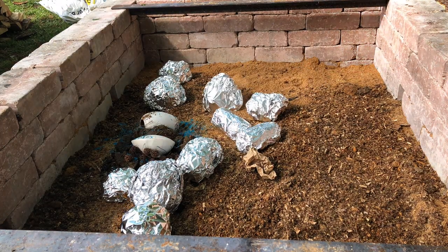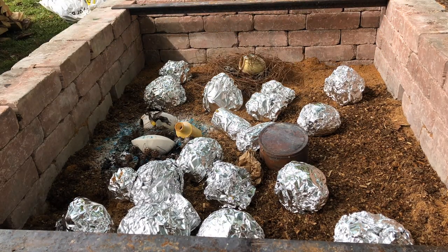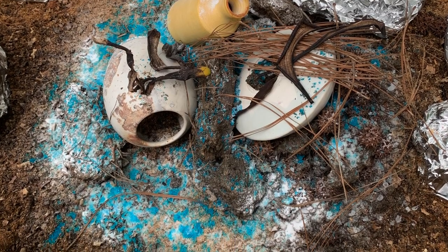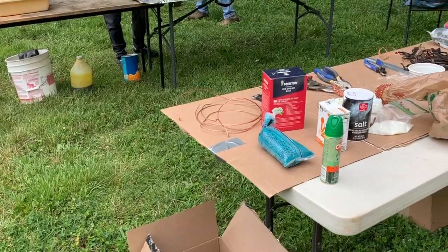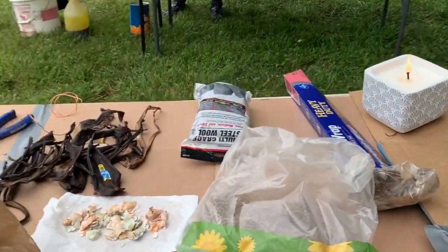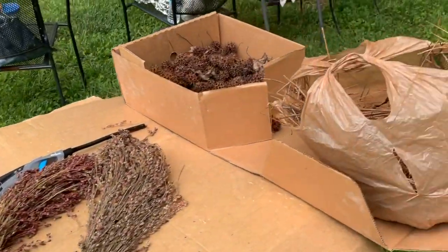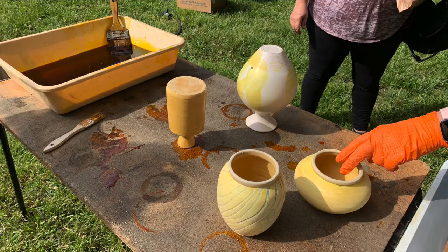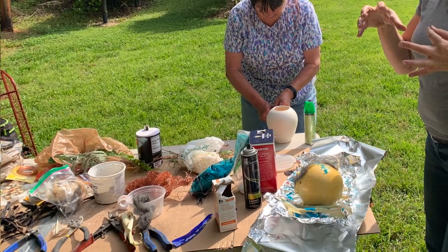There's about four to six inches of sawdust on the bottom, and then we put the pots in. Most of them were in aluminum foil saggers, but some are raw pots in there with cow dung, paper, sawdust, and Miracle-Gro around the raw pots with baking soda and salt. The sacrifice pots have various things inside — anywhere from steel wool, copper wire, copper scrubby, stretched-out feathers, coffee grounds, banana peels, orange peels, apple peels, and ferric chloride.